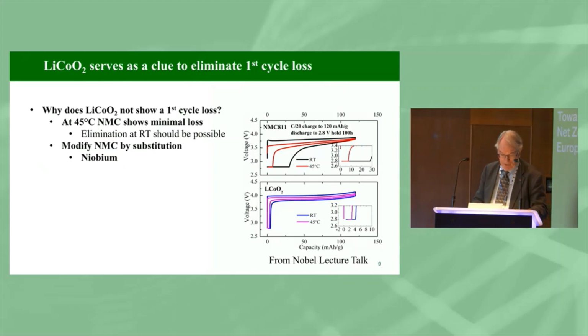So we have clues that we should be able to solve this. Lithium cobalt oxide itself does not have this first cycle loss. So what we did was a study, and we'll compare 811 with cobalt oxide. The black here is room temperature. In this case, we've now only charged up partway, and discharged it. If we hold it now for 100 hours, we get all lithium back in at 45 degrees, much faster. Clearly kinetic control. And lithium cobalt oxide, there's no issue. There's no loss there. So clearly we should be able to get our material and try to make it behave more like the pure lithium cobalt oxide. And that's what we've been doing.